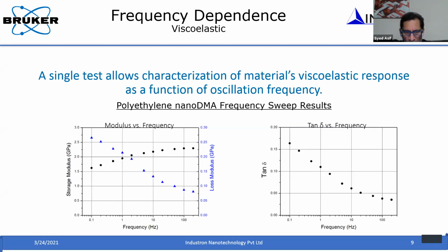So in a nutshell, you can directly measure the viscoelastic response of the material by measuring its storage and loss modulus. For example, here for a polyethylene polymer, you can see that the loss modulus as a function of frequency is decreasing from 0.1 Hz to 100 Hz, and the storage modulus is basically increasing as a function of frequency. This is what you typically expect for a polymer material. If you take the ratio of loss to storage modulus, you get the tan delta. So this is what we can do with the DMA technique.